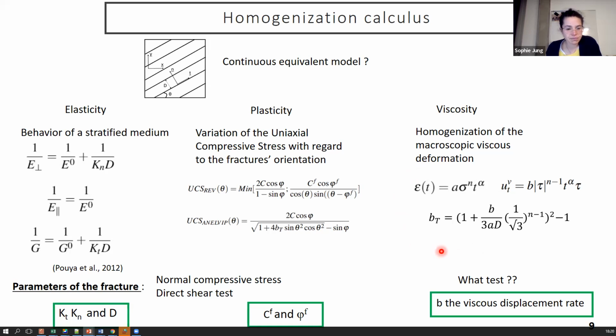The strength, or the success, in this calculus is that now we have a good understanding of the parameters of anisotropy, as they are a function of fracture parameters that are completely understandable and that we can actually measure through mechanical tests. For instance, regarding the elastic part, the parameters that need to be measured are the tangent and normal stiffness of the fracture and the fracture density. The stiffness can be measured through normal compressive stress and direct shear tests.